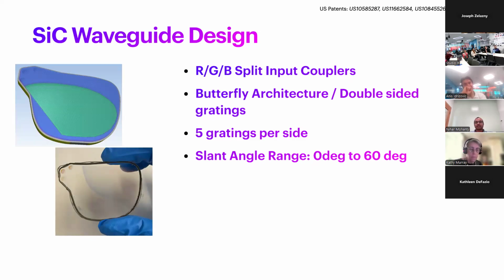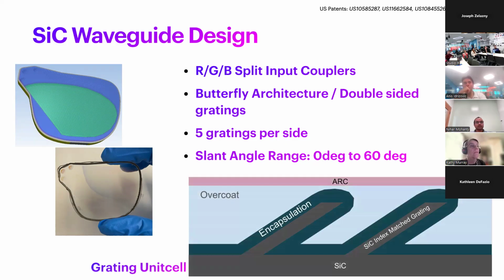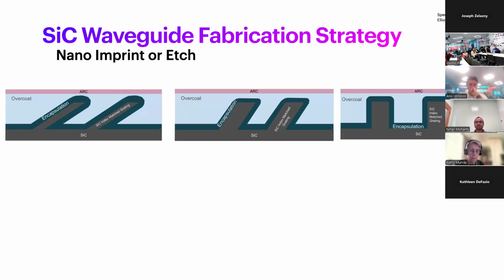The optimized high-performance grating design architecture for Orion had split red, green, and blue input couplers and discrete out couplers on each side with a slant angle for each grating optimized for performance and ranging from binary at 0 degree slant to 60 degree slanted gratings. The grating unit cell was comprised of a high index grating that is index matched with silicon carbide with an encapsulation layer, followed by the grating immersion layer that I explained before called the overcoat, and being topped off by a simpler single layer anti-reflective coating. While this unit cell might seem daunting, it was critical to enable the high performance of Orion.